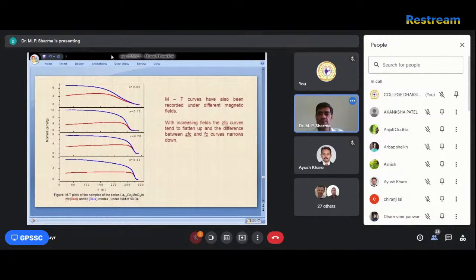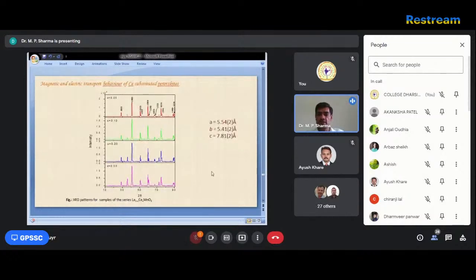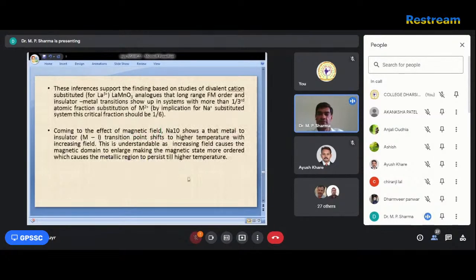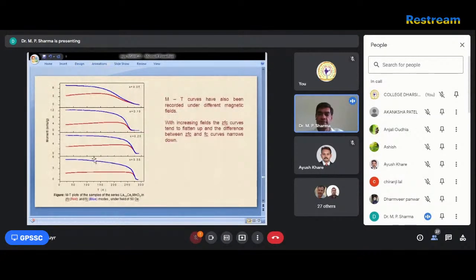Okay, so this is the XRD, but in the same situation there are some impurities. When you increase the doping amount, the impurity increases because the peak of this impurity phase is given higher. But again, the CeO2 is non-magnetic, so there is no effect on magnetization. So the magnetization is for LaCeMnO3, where Ce is 0.05, 0.1, 0.2, and 0.3.